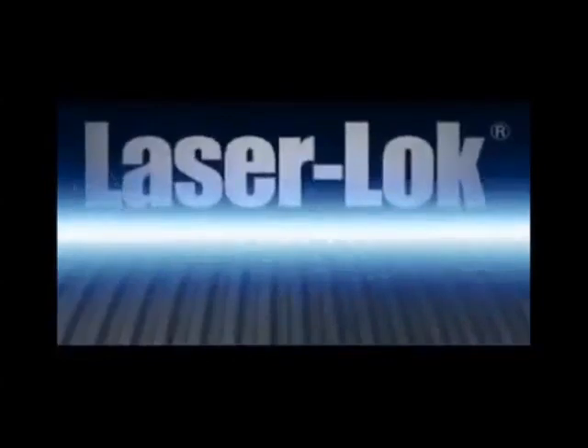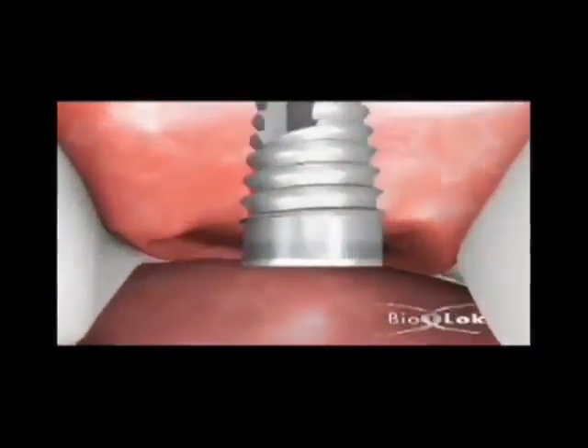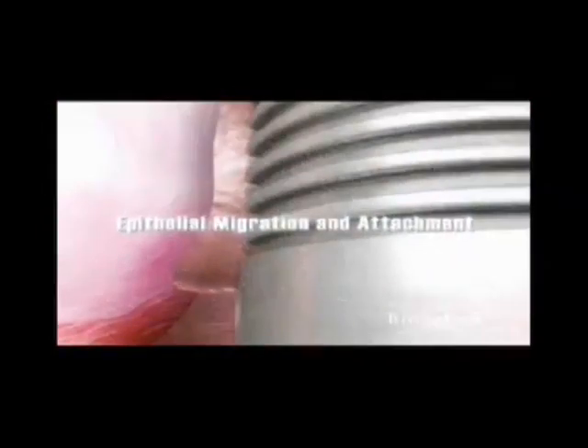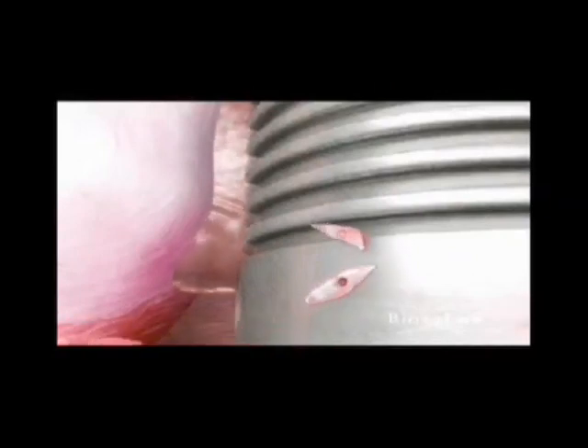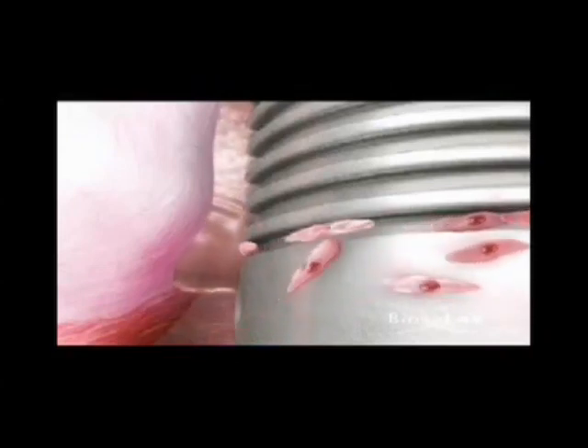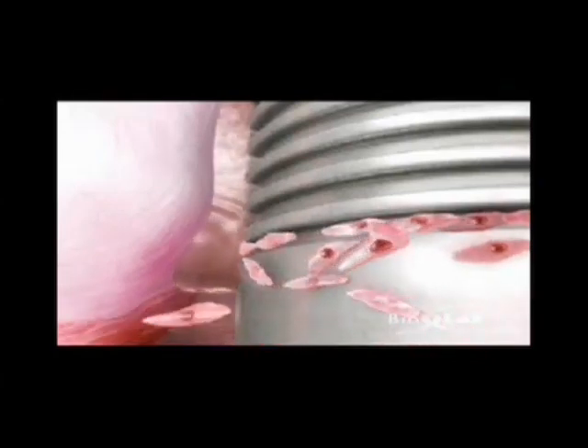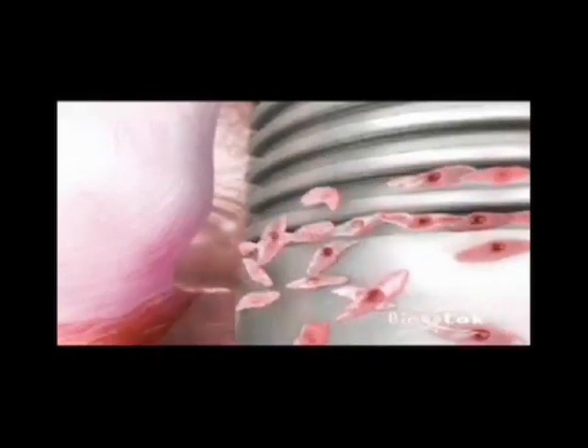The Laser-Lok Bioaffinity Collar, programmed cell response for soft and hard tissue attachment. Laser-Lok's revolutionary computer-controlled laser ablation technique utilizes a pulsed excimer laser to form the unique repetitive geometry of its 8-micron and 12-micron horizontal cell channels in the Laser-Lok Bioaffinity Collar. The 8-micron cell channels of the Laser-Lok Bioaffinity Collar inhibit the vertical migration of epithelial cells, maintaining space for fibroblasts and osteogenic cells to attach to the implant.